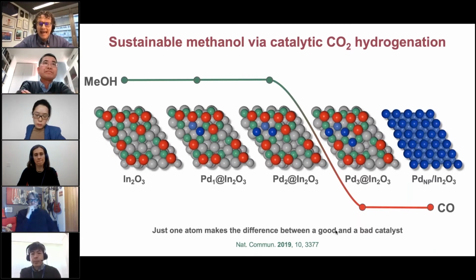So in order to combine the enhanced hydrogen activation that palladium brings, maintaining the selective character of indium oxide, atomically dispersed palladium sites are required, which is achieved by single atoms or dimeric palladium species. As long as there is a little bit of clustering, leading to a 3 or 4 palladium atom cluster, then the reverse water-gas shift kicks off and the main reaction product switches from methanol to carbon monoxide, which is what you don't want. In other words, the difference between an outstanding catalyst and a mediocre catalyst is just 1 palladium atom. This is the level of precision we are striving for today in heterogeneous catalyst design. 1 atom too much or 1 atom too little matters a lot.